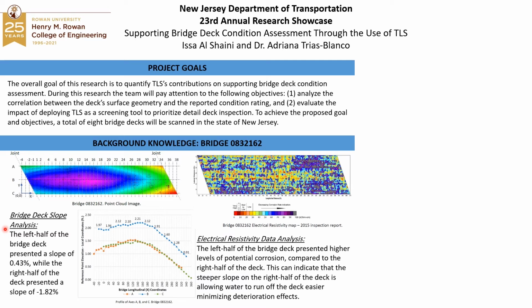By combining the 2 results from the 2 different assessment methods, we can indicate that the steeper slope on the right half of the deck is allowing water to run off the deck easier, minimizing deterioration effects. On the other hand, for the left side, the flatter slope is sometimes causing water retention on the surface of the deck of the bridge, causing the bridge to deteriorate and the steel to corrode. It took us 2 different assessment methods to get the result that water retention is causing the left side of the bridge to be at higher levels of potential corrosion.